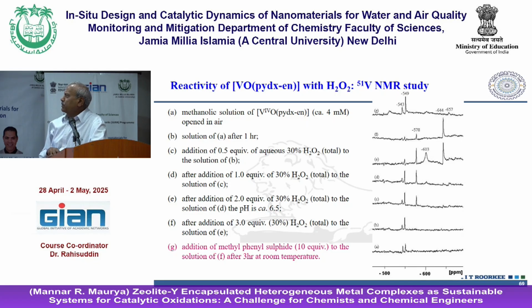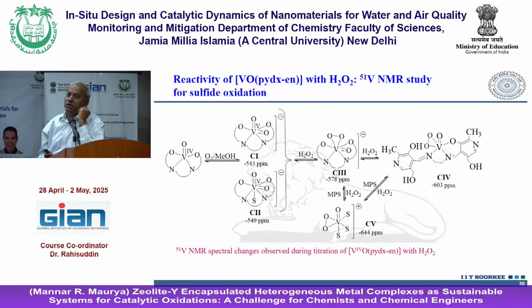Then moving further, more peroxo species are found, and then you add the substrate. After 10 equivalents, the last one you will see is methyl phenyl sulfide. Immediately the peak due to peroxo has gone. That gives a clear indication that the peroxo is transferring oxygen to the substrate. So this is an alternate way to find out the reaction mechanism.